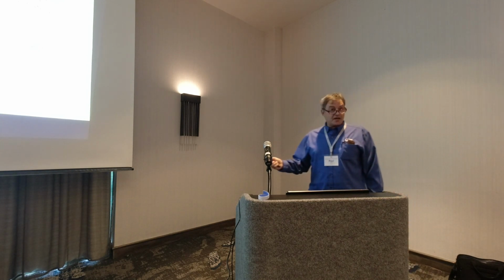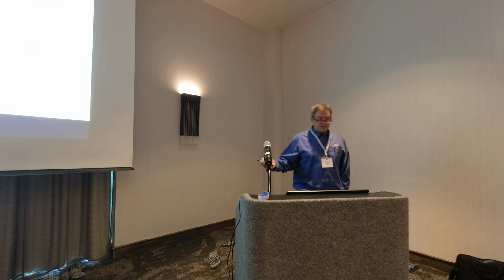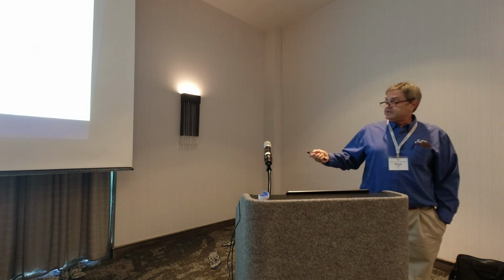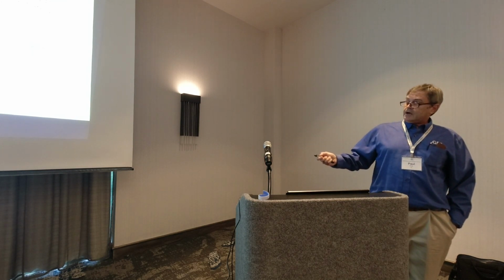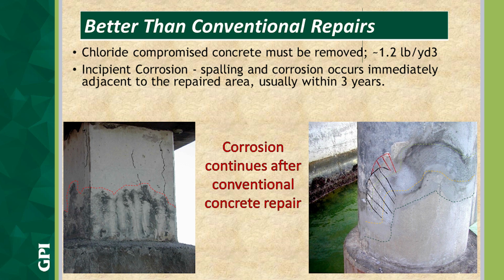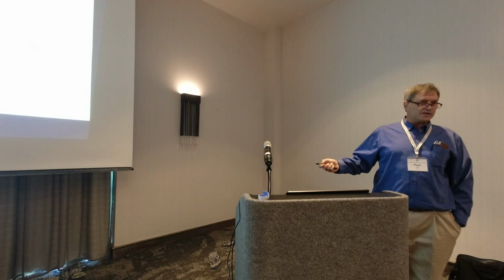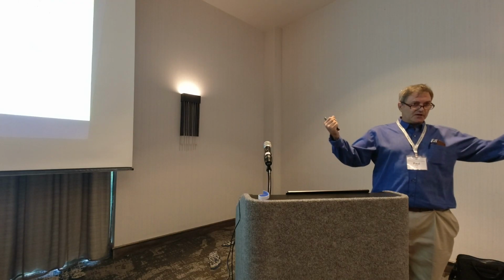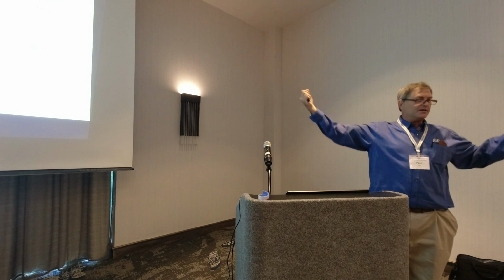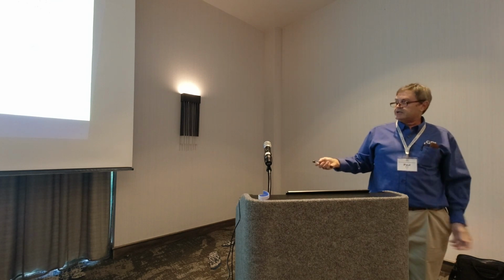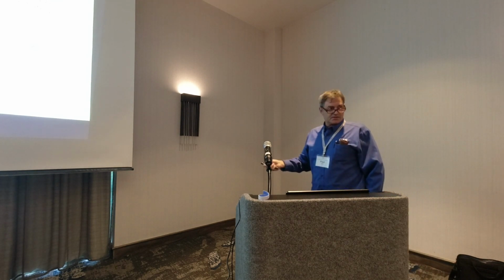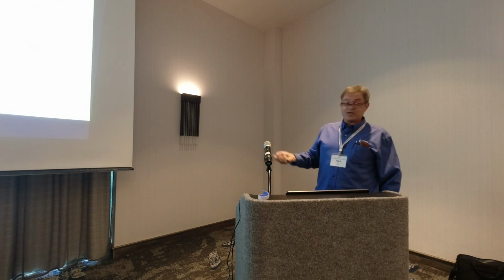We see this all the time in bridge decks, all the time in substructure. And the reason is this concrete up here is still all chlorinated and still very electronegative. Down here, we've just put in brand new concrete that has no chlorides. That sets up our corrosion cell. We've got a high energy area and a low energy area. So unless you isolate the bar and do some things to prevent that, you're just going to chase your tail.